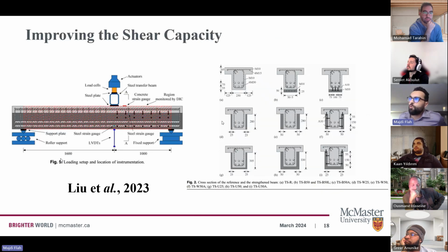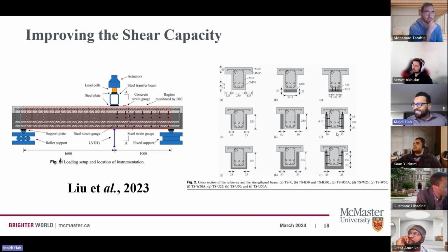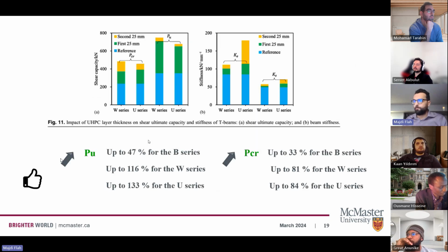This is another study that tried to investigate the shear capacity. It's a concrete T-beam. They tried more or less the same configuration of having a bottom layer, side layers, and a U jacket. So you can see in some of the studies, they tried to put some shear studs. The idea there is because they started noticing some failures in the behavior and the shear behavior. That's why they tried to put some studs in order to limit that reduction in shear.